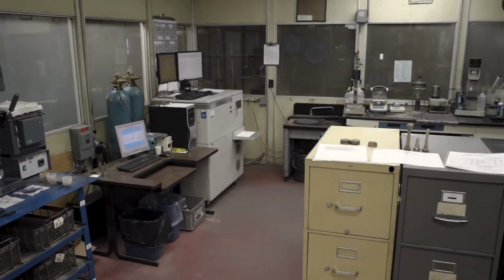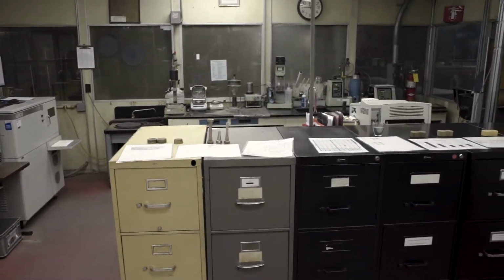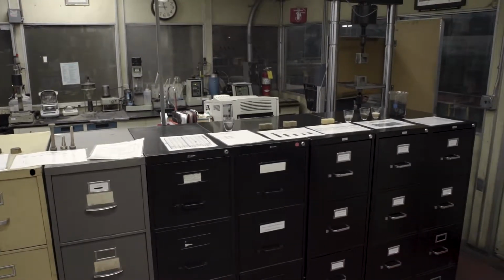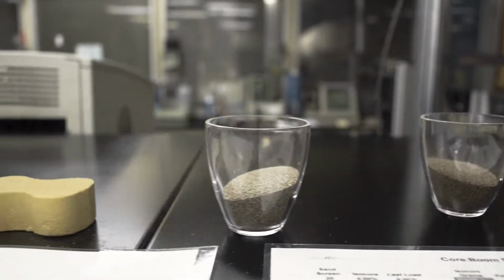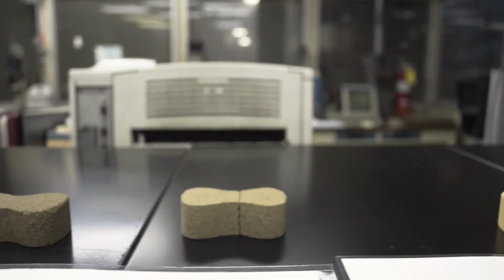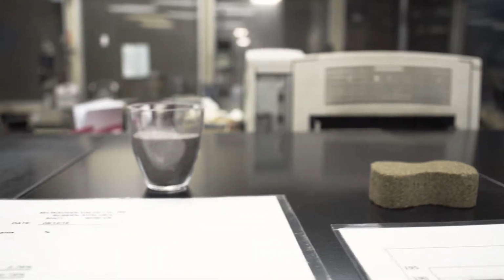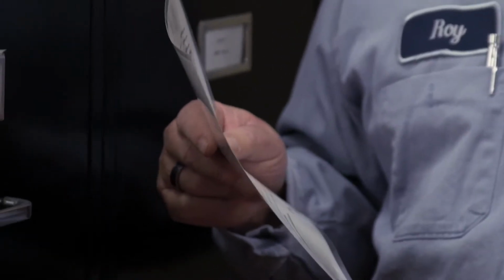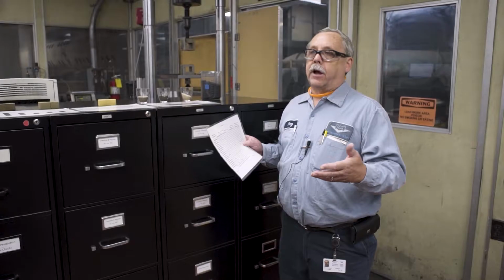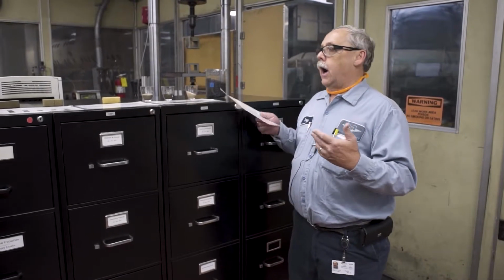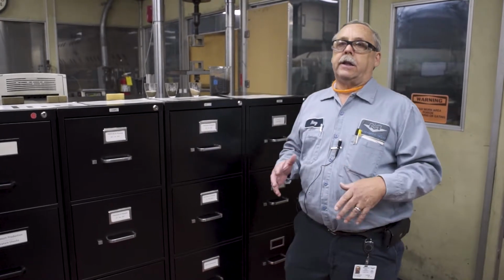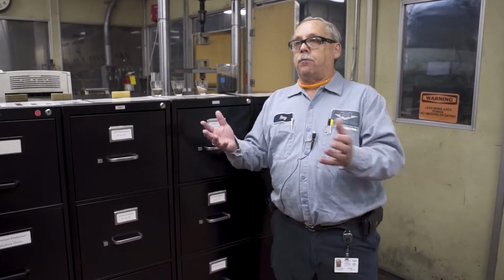Along with that, we pull a sand sample like this from the molding line right at the molding machine, and we do additional tests. We'll do several additional tests, 10, 12 different tests. Grain fineness, LOI, which is combustibles type thing, loss on ignition. We do permeability, the ability to get gas out of a mold. And when we pour metal into the mold, and we got the cores, we got to get the gases out. So we got to have the mold permeable to release the gases.